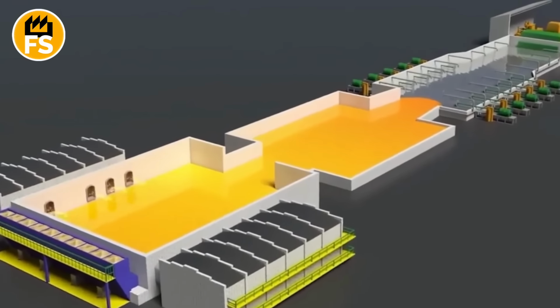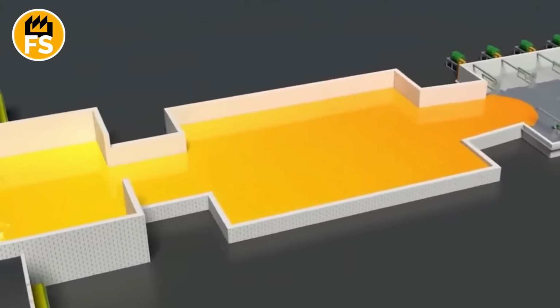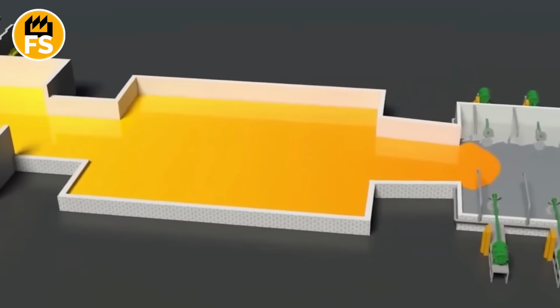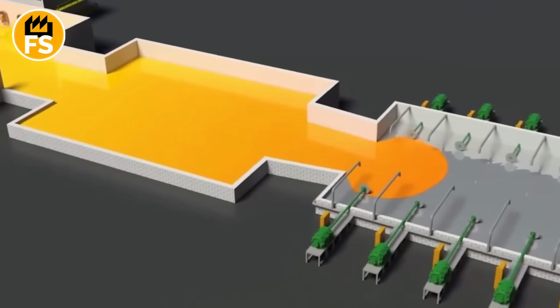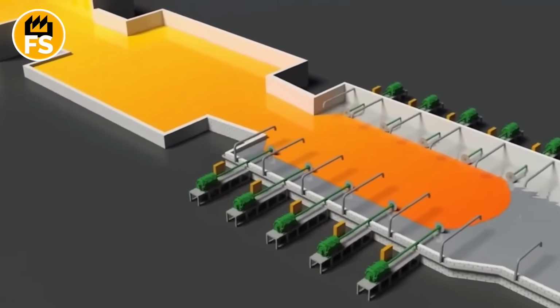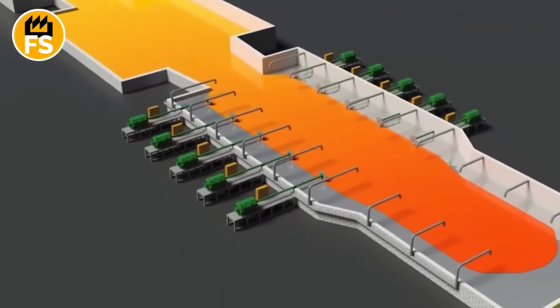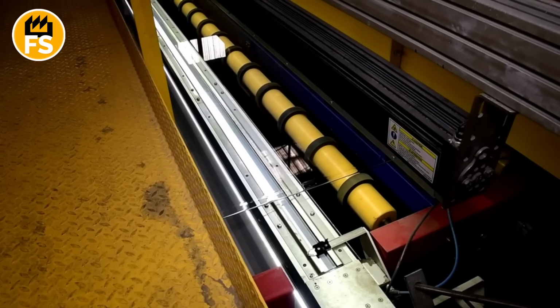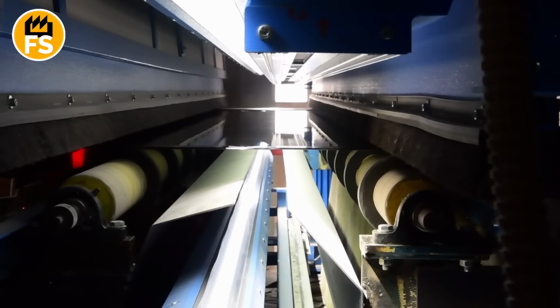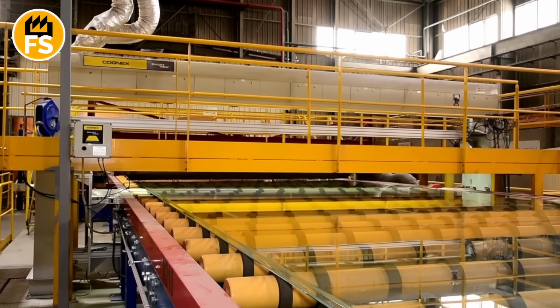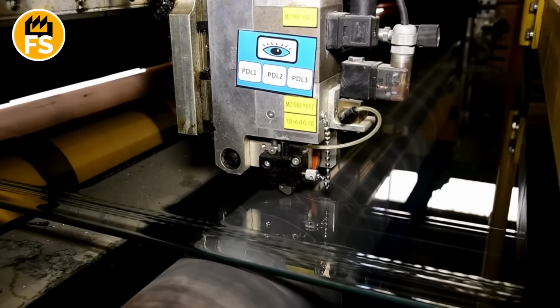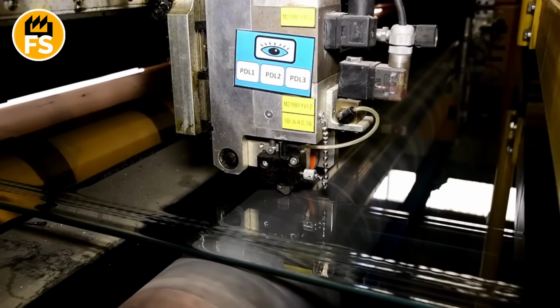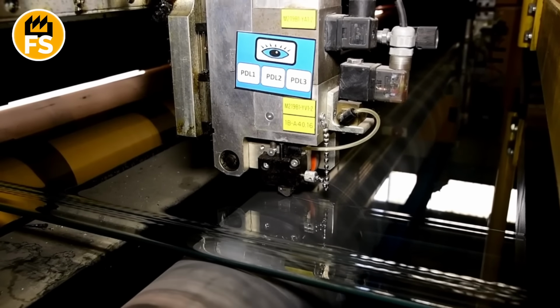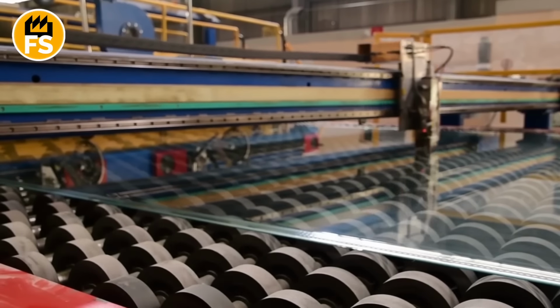After melting, the glass mass undergoes a forming process, which in modern production is most often performed using the float method technology. Feeding the glass mass, the liquid glass flows out of the furnace and onto a bath of molten tin. Thanks to the high density of tin, the glass mass spreads evenly over its surface. Under the influence of its own weight, the glass forms a perfectly even and smooth surface. By gradually lowering the temperature, the glass acquires hardness. At the exit of the bath, it can already be processed. The float method allows for the production of glass sheets with precise geometric parameters and high surface quality.